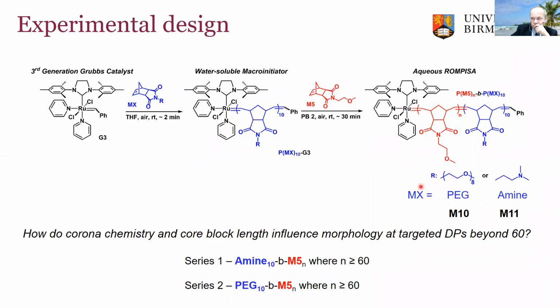We've done this reaction with two different systems, one which has a PEG pendant group and one with an amine, to try and explore how the corona chemistry and core block length influence the morphology. And we're looking at DPs beyond 60 because this is where we think we see interesting morphological development.